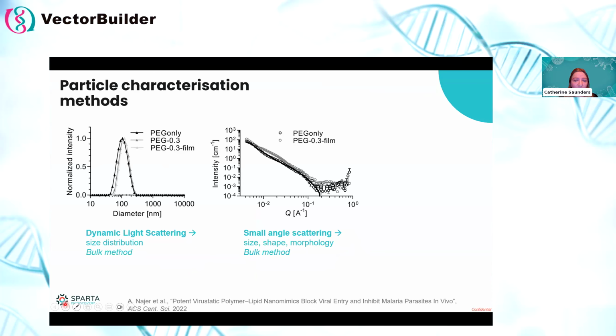So when making these particles, there's a whole suite of analytical tools available. Here, what was used was dynamic light scattering, a very standard technique to determine the size distribution of more homogeneous samples. There was also some small angle scattering done, a technique which can tell you about particle morphology, including size and shape. The main conclusions from these techniques were that these particles were around 100 nanometers and they were lamellar particles.